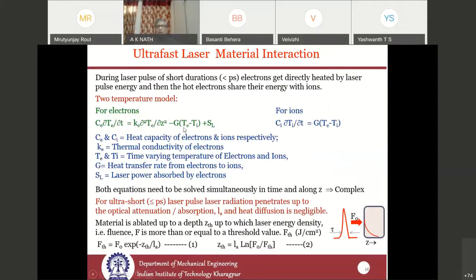Finding the temperature rise of electrons and ions and the material removal becomes a very complex process, so people have tried to utilize empirical relations derived from experimental information. One can find that there is a certain threshold of laser intensity, or laser fluence, up to which the material gets ablated.